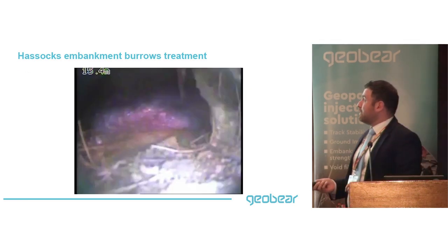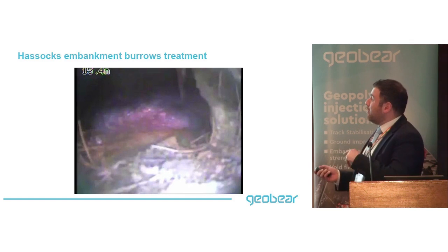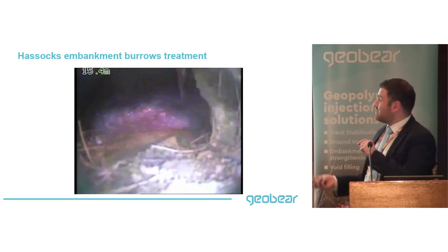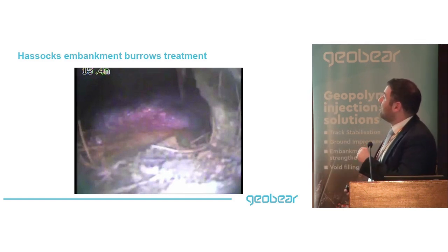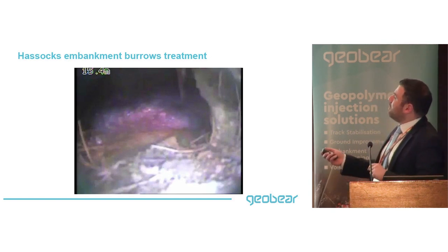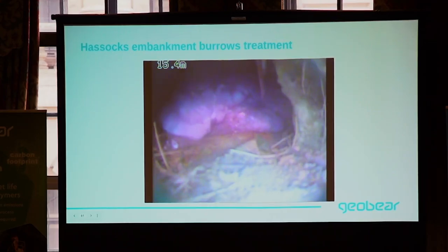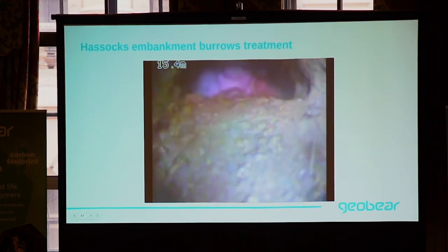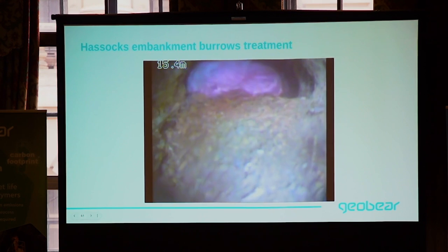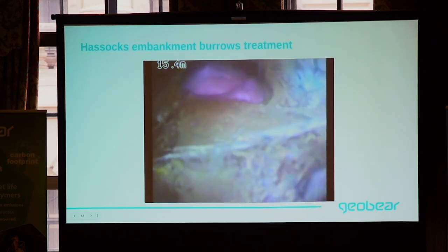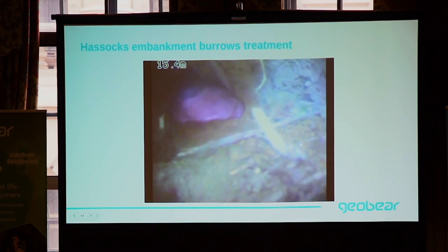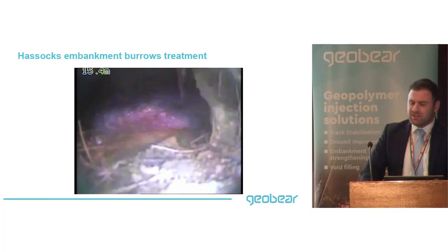I've got a nice clip, one of my favorite clips, of the geopolymer spreading into a badger set - that's a CCTV camera recording. As you can see, the polymer is slowly being injected and expanding within the badger set, and as it's getting closer to the camera, the operator is pulling the camera slowly so they can see what's going on. You can see the polymer just starting to spread within the badger set and expand and fill it up nicely. That was a good validation to see what is really going on inside the badger set during the injections.